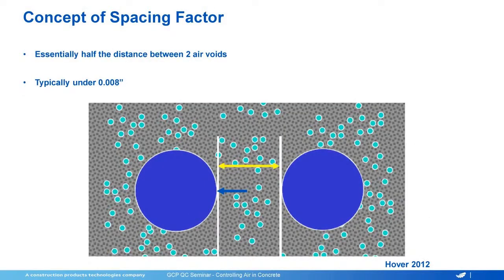Spacing factor, again, typically less than the 0.008 is the number that we see specified if air void is specified. And that's basically half the distance between the two air voids is what the 0.008 represents. So not very far.